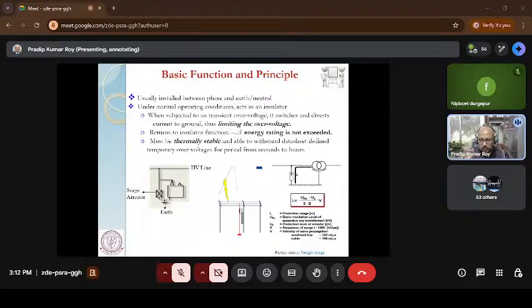Now, during the surge, it is found that the temperature can go around 120 to 140 degrees Celsius. So if the temperature is not dissipated properly, sometimes the performance of the surge arrestor deteriorates. In that case, the equipment should be thermally stable, and there should be some provision to dissipate that heat immediately after the surge goes back.